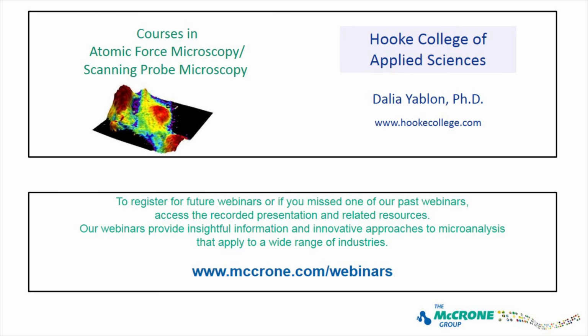Another question that's come in is what calibrations are necessary? I mentioned this at the end, that there are two main calibrations you need to do force curves effectively. Actually there are three, but the third one is hard to do. The first two are your spring constant calibration and your detector sensitivity calibration. You need those to convert from volts, which is what you're actually measuring in force spectroscopy, to newtons of force. The third calibration is extremely tricky, the Achilles heel of AFM mechanical measurements, and that is tip shape.